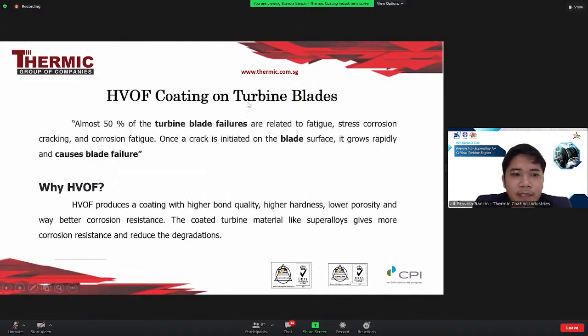HVOF coating on turbine blades. Almost 50% of turbine blade failures are related to fatigue, stress corrosion cracking, and corrosion fatigue. Once a crack is initiated on the blade surface, it grows rapidly and causes blade failure. Then it needs to be coated to improve or extend the life of the blade. Why must it be HVOF? HVOF produces a coating with higher bond quality, higher hardness, lower porosity, and much better corrosion resistance. Coated turbine materials like superalloys give more corrosion resistance and reduce degradation. We saw before from the table that HVOF is better than other processes for the blades.